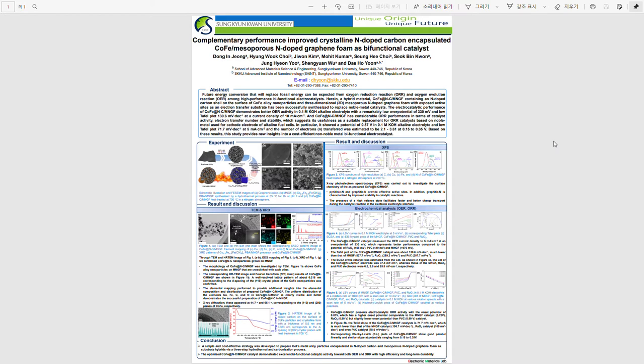We conducted the following analysis to verify the performance and phase of the synthesized catalyst materials. Through TEM analysis, it was confirmed that the cobalt-iron compounds grew well on the graphene foam used as the substrate, and the N-doped carbon shell was well formed on the surface of the cobalt-iron compounds.